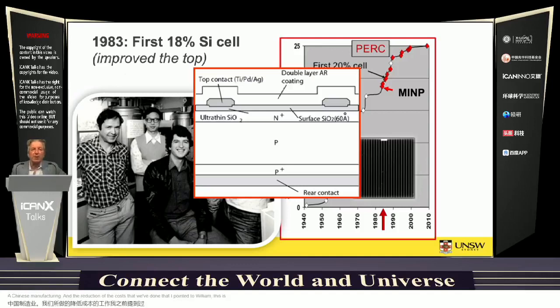This is the structure we used. Our main secret weapon was employing oxides along the top surface of the cell to reduce the electronic activity of that top surface. So this is a technique that was well known in microelectronics at that stage, but there were some additional challenges in applying it to solar cells in that you couldn't have it too thick. So we even put it underneath the metal contact. So this was our particular contribution to the technology, this tunneling type of contact here. So it reduces the electronic activity of the metal to semiconductor interface that you'd get without it there.